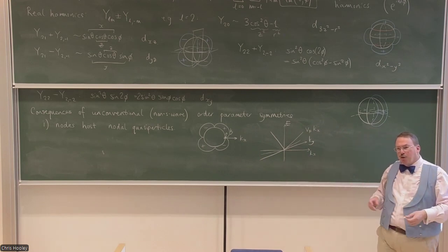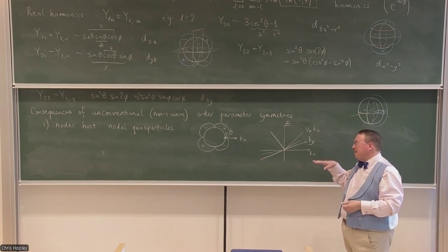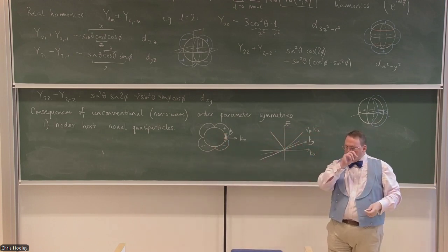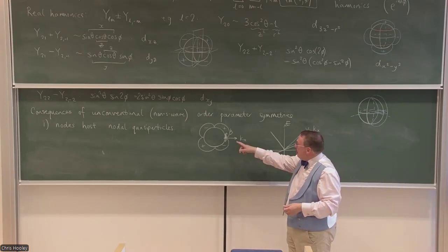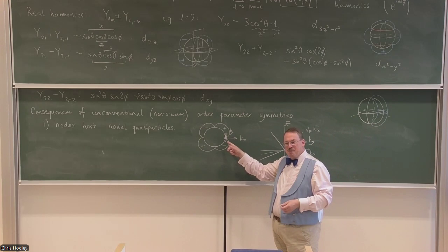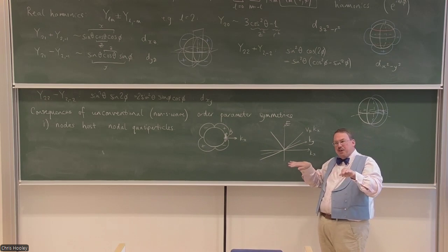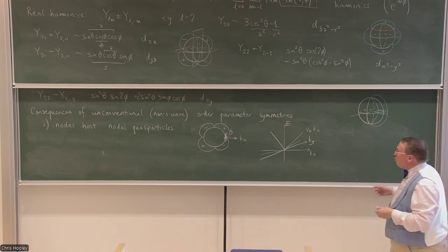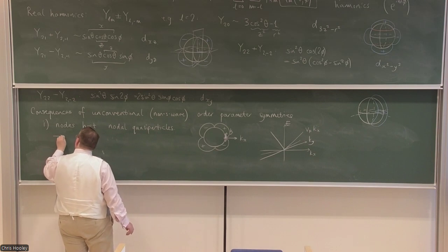And there are interesting physical consequences associated with that, which is, for example, if you excite nodal quasiparticles, they spread round the Fermi surface much more than they spread away from it. So if I put a few nodal quasiparticles in somehow, they make a little banana-shaped Fermi surface, because if I imagine filling this anisotropic cone with liquid, the liquid would go much further in the flat directions than it would in the steep ones. So that's one consequence of having the nodal quasiparticles. What does that cause?